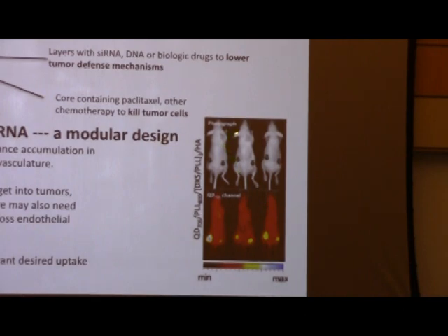So here's a picture of mice. They have tumors on their backs, and you can see that at 24 hours, we used a quantum dot in this case and layered it with our layer by layer film, that our layered quantum dot particles are accumulated in the tumors. If you look at an earlier time shot, you would see that at first the entire animal lights up, and the nanoparticle is everywhere in the bloodstream. You can see that because it's in the bloodstream, it goes everywhere where blood vessels go, but it gets cleared everywhere but in the tumor where it hangs around.